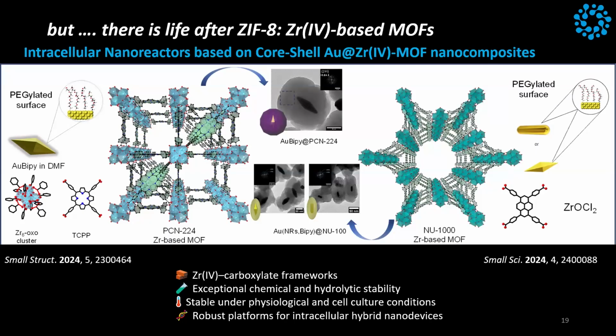Because I don't want the spheres. In the case of magnetic nanoparticles, it's fine. But if I destroy the core when I'm making the nanoparticles, it's not useful for me. So he found, and at the beginning I didn't believe it, that by pegylating the nanoparticles with PEG, something that we always do, these nanoparticles can sustain increased temperatures.